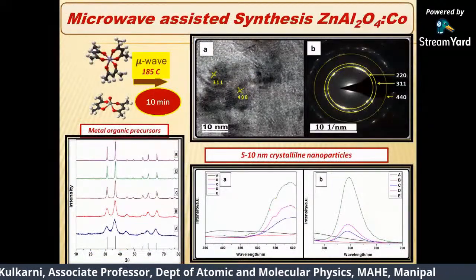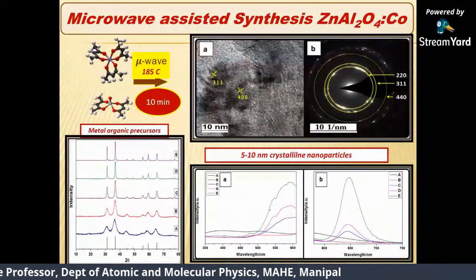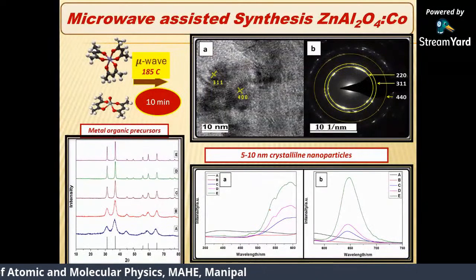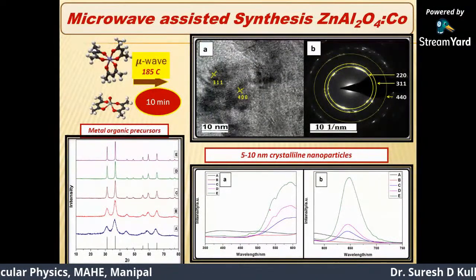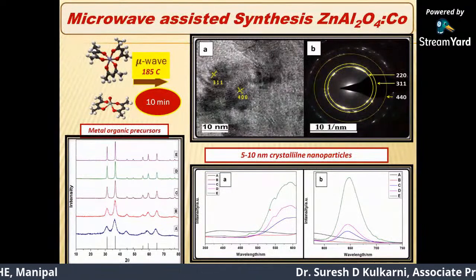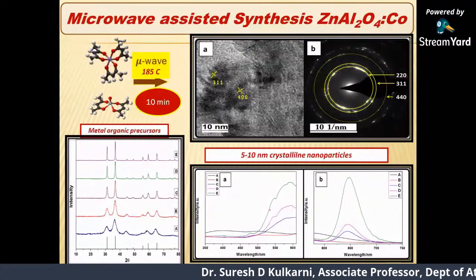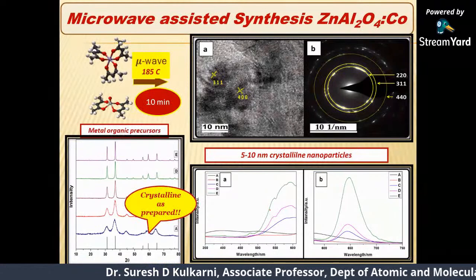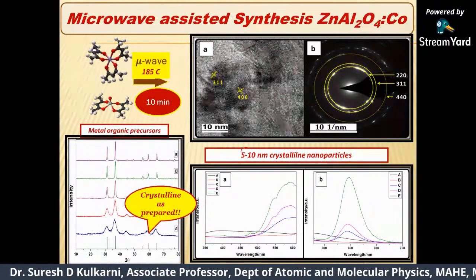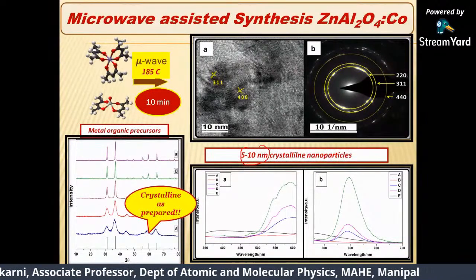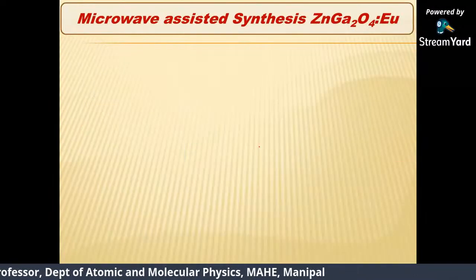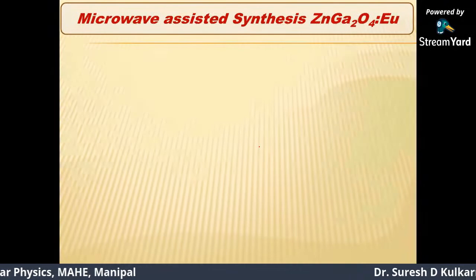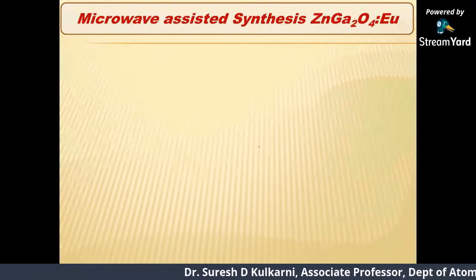Similarly, we have put cobalt as a dopant, and you can see again we can do all the same things. I will not spend much time on this. Again, here we are using metal organic precursors. The material is crystalline, and the particle size is in the range of 5 to 10 nanometer. Later we started synthesizing a well-known phosphor called zinc gallate with europium as a dopant.